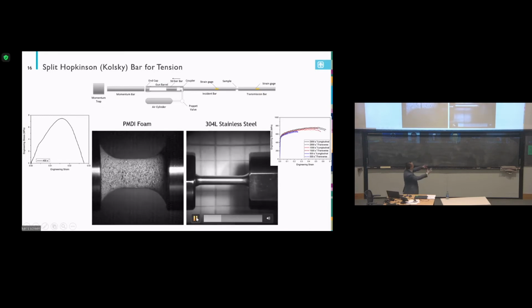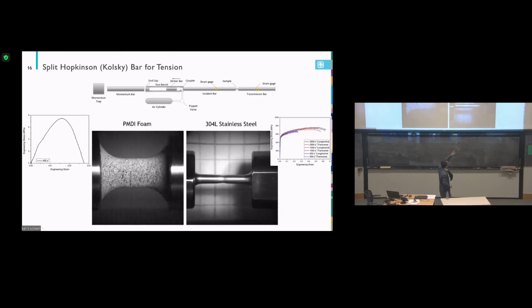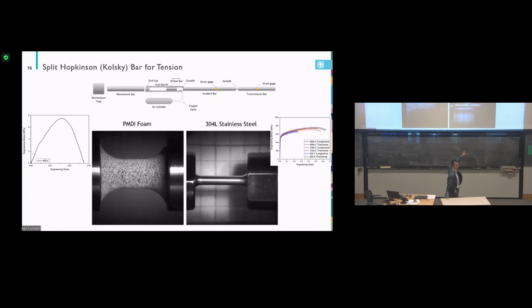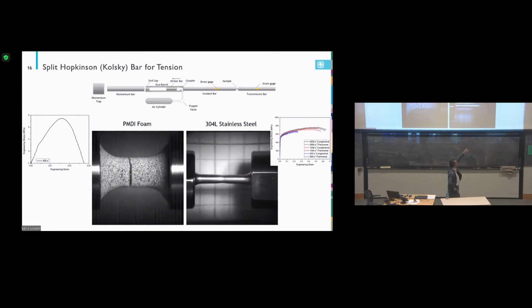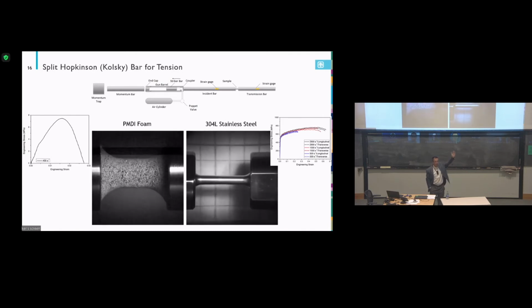And this is very typical for metals. You can see when we pull it, you see it start necking, then eventually fracture. So this image didn't capture the eventual final fracture, but you can see the necking over there. And the stress-strain curve follows a similar yield and plastic flow like this. So this is the tensile test.